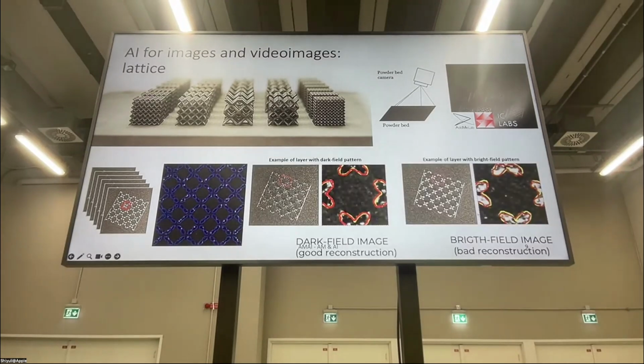There's a lot of pain because each layer is different from the previous one, unfortunately. So it's not that you can tune the algorithm on one layer and that's it for the whole job, because depending on the scan strategy and the illumination condition, you can have a lot of differences layer by layer. And so you have to tune the edge detection algorithm depending on whether you are in a dark field image or a bright field image.